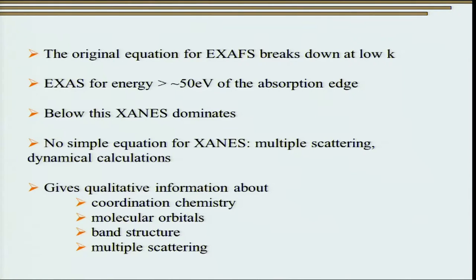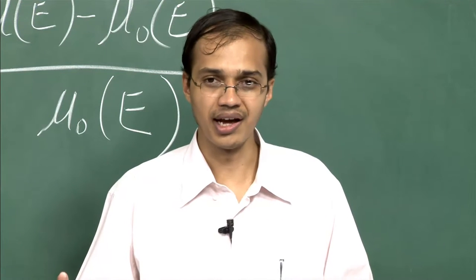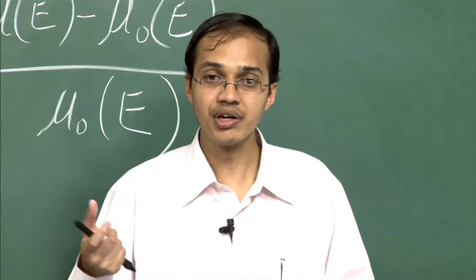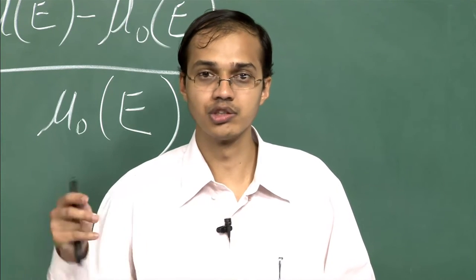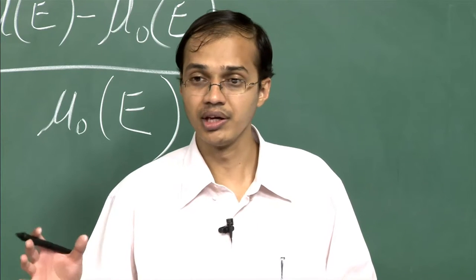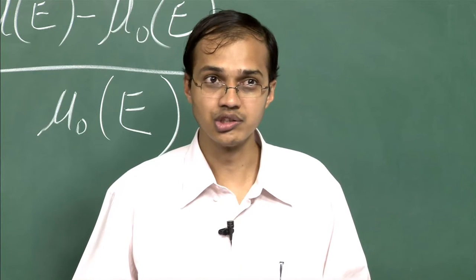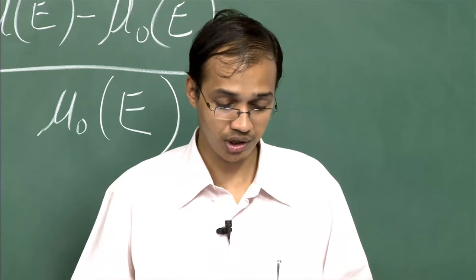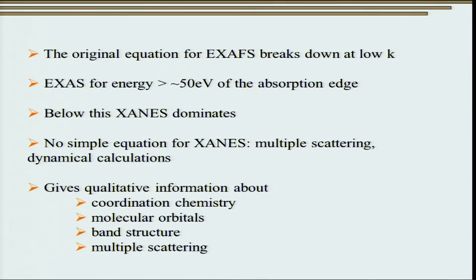The original EXAFS equation breaks down at lower k, where we have near edge X-ray absorption fine structures (XANES/NEXAFS). In this energy range, there are multiple scattering events and dynamical calculations must be incorporated. XANES is therefore used only as a fingerprint technique — if we see particular peaks in the XANES spectra, we can say a particular element is present. However, quantitative analysis of this technique has not been fully developed. XANES does give a lot of qualitative information about coordination chemistry, molecular orbitals, band structure, and various multiple scattering events in a material.